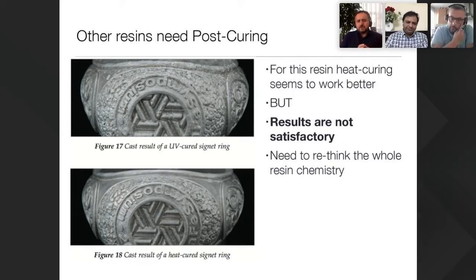So what I'm trying to say is that if you post-cure or heat cure one resin, you may have some improvements that change the chemistry of that printed part, which may affect the reaction between the resin and the investment in the burnout. But this may not be satisfactory, and the result may not be good enough, because your starting point is not really a good castable resin, or the right appropriate castable resin.